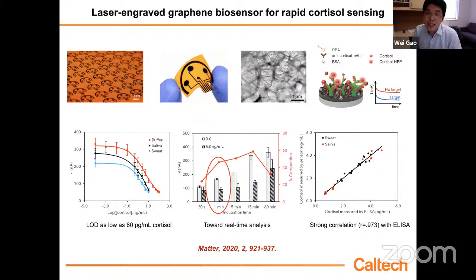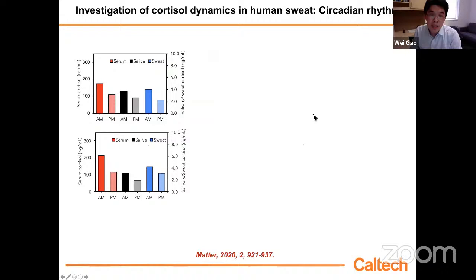So total is within one and a half minutes, we can get one measurement for stress hormone. So we actually validated our sensor in sweat and in saliva using the gold standard ELISA kit. We found that our sensor can provide pretty accurate readings. So if we apply our sensor on human studies, we found that we can see the circadian rhythm of the stress hormone cortisol. In the AM and PM, you see serum, saliva, sweat, a very similar pattern. Morning cortisol level is higher than PM.